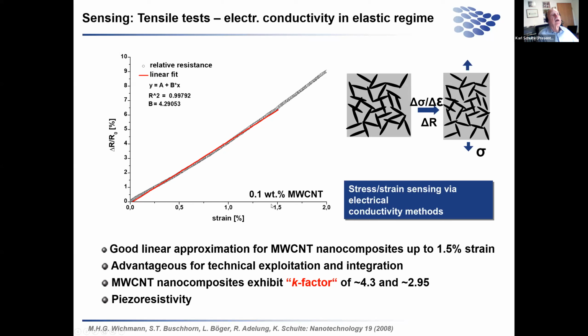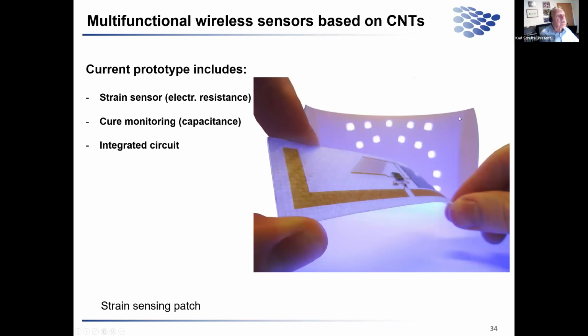If we look at what happens here, schematically: we load it, and the distribution of the nanomaterial in the solid epoxy somehow changes with the strain and deformation of the matrix. This gives us the possibility to measure increasing resistance, partly due to the fact that, for instance, these contact points are further away, and that increases the resistivity.